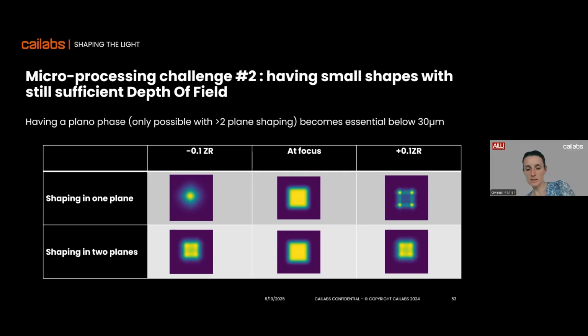And in this example, we demonstrate what's happening when you have the same square at focus, but you do beam shaping using just one plane, so typically using one diffractive optical element. Well, you can see that at 10% of the Rayleigh range, your shape is already killed. So 10% of 80 micron is actually 8 micron, which means you end up with an extremely small depth of field. And if you manage to preserve the phase, to have a plano phase at the point where you have your beam shaping, you can actually have a way larger depth of field for your shaped beam.